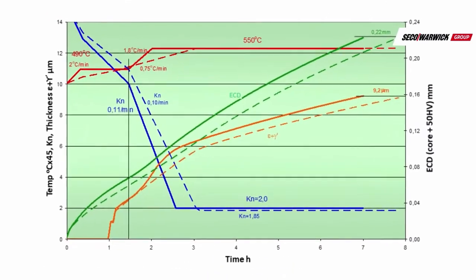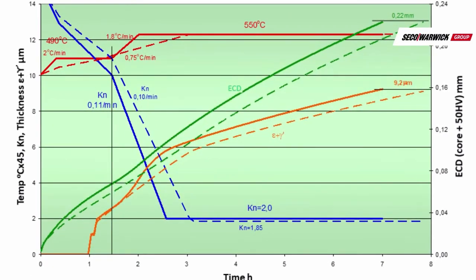Presented on the graph as dotted lines are real values of temperature and nitriding potential. With lower speed of load heat up and slower potential reduction, the growth of the diffusive layer is also slower. In order to receive an exactly identical layer, its thickness, structure and effective depth, the time of the second nitriding stage was longer by 50 minutes and nitriding potential was reduced from 2.0 to 1.85.